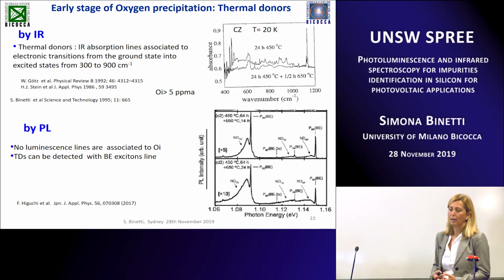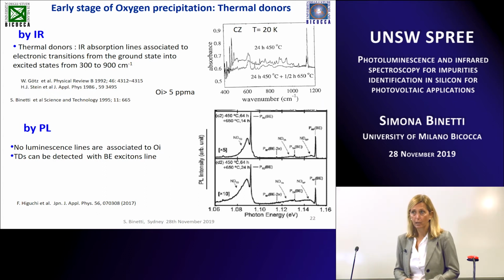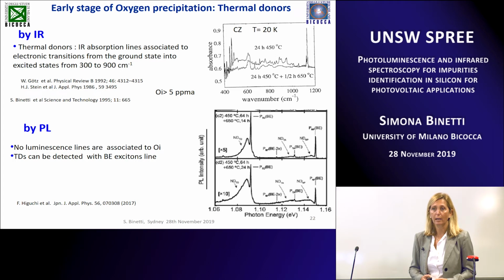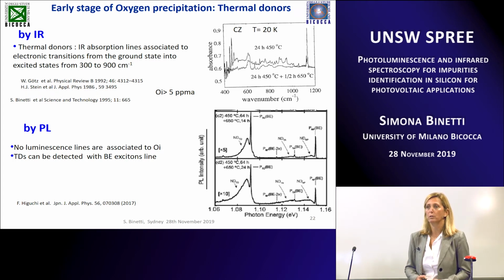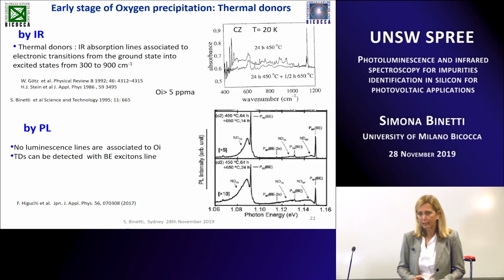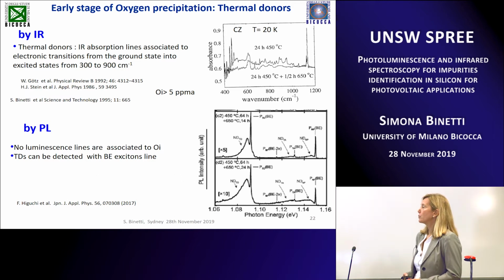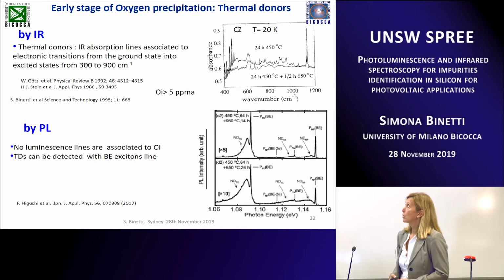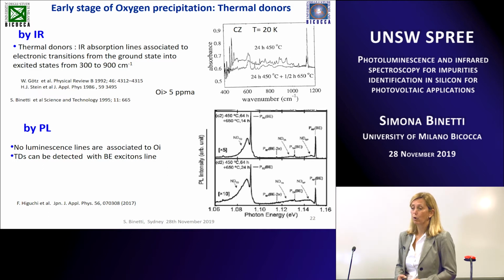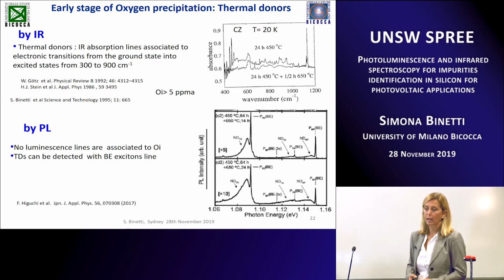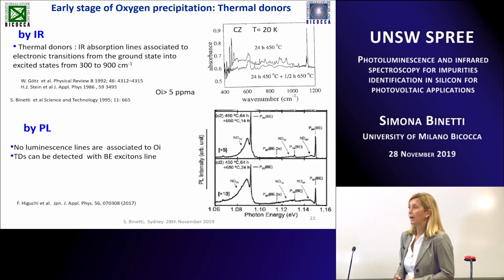This work has been done many years ago for microelectronics application. You know that in silicon, oxygen precipitation gettering is one of the most known processes in order to improve the lifetime and the performance of silicon for microelectronics application, but it can be useful also sometimes to know for photovoltaic application. Thermal donors, which are the small oxygen nano-precipitates usually formed after thermal treatment around 450 degrees C, but you can have them in your ingot, because they can be formed also during the cooling process of your ingot, can be detected by infrared spectroscopy, like the dopants that we have seen, because you can see this is the standard range.